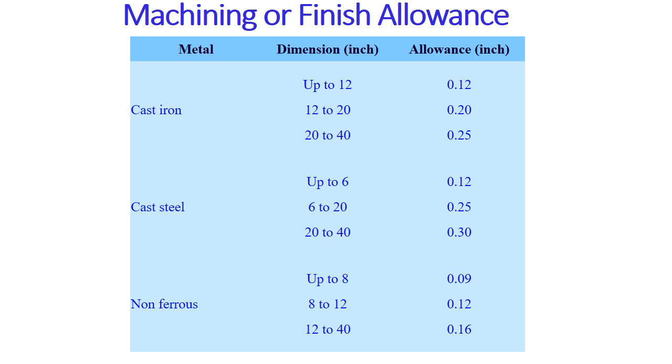It generally ranges from 4 to 5 millimeter, and mostly we try to put that extra machining stock at the top of the casting, because all the sands and slags try to float up at the top of the mold, so they can be easily removed by the machining process.